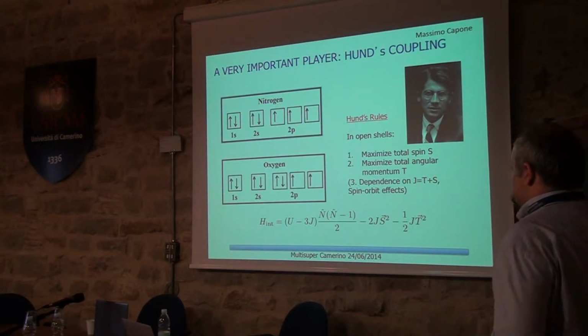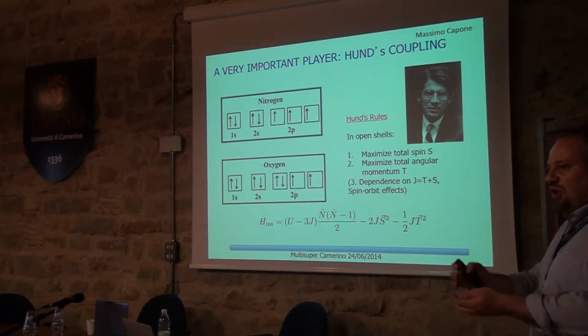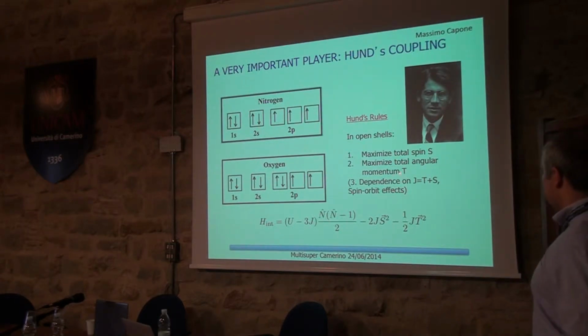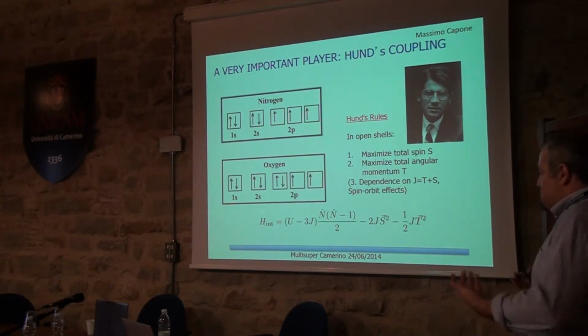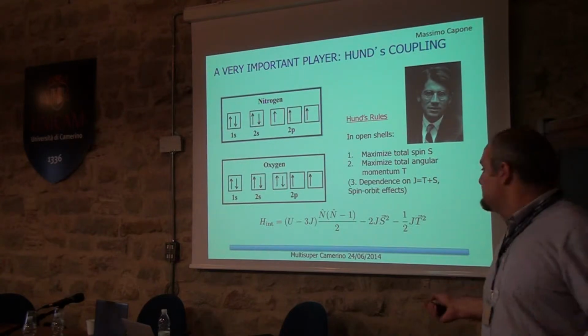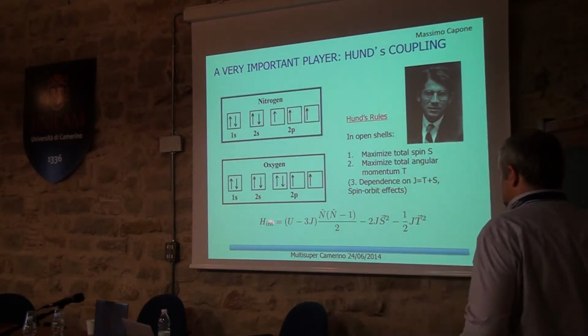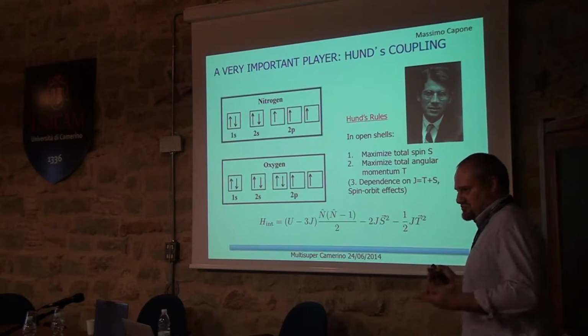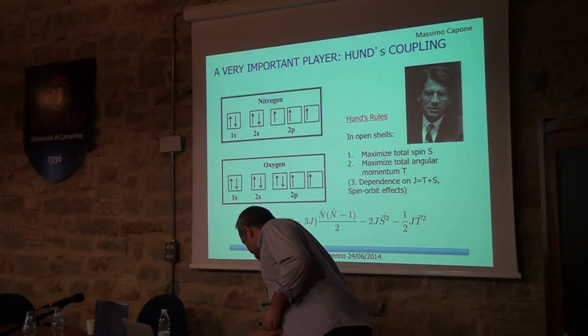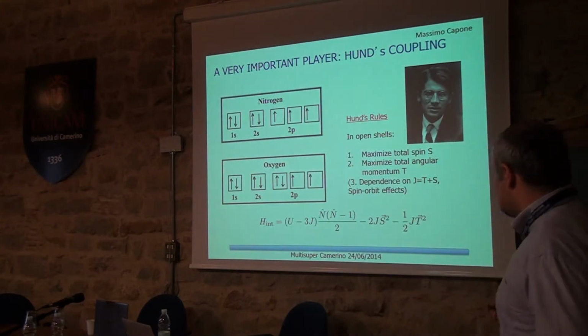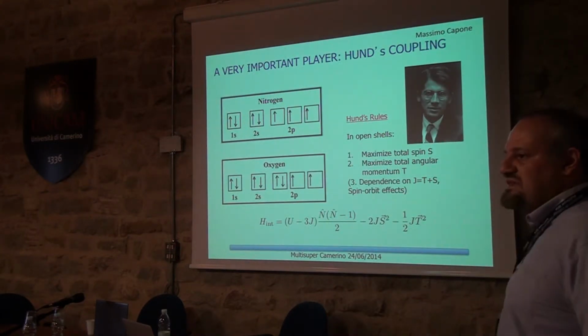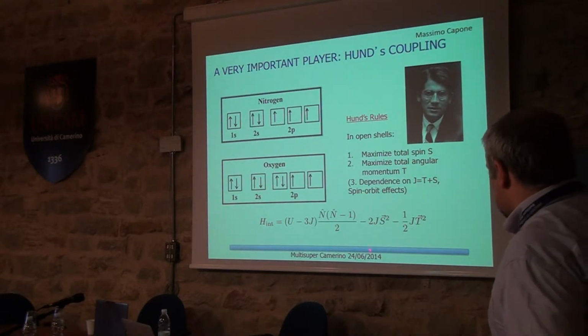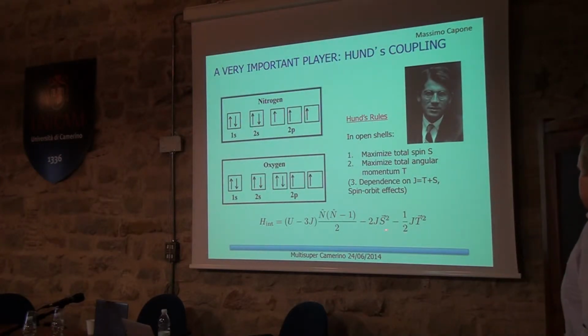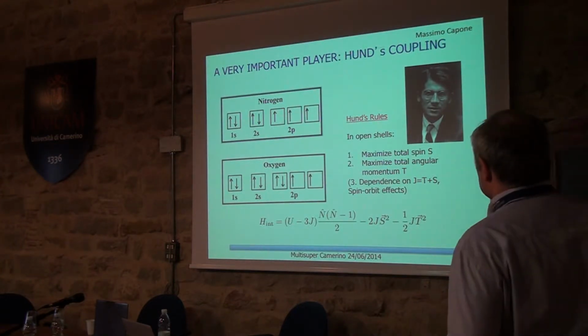It wants to, first of all, maximize the total spin of electrons sitting on one atom, and then, as a second prescription, maximize the total angular momentum on the same atom. The third one is not related to the same exchange, it's just due to the spin-orbit coupling. So this is what you do to build your atomic configuration. That's essentially how it looks when you write it down in the Hamiltonian. This is written in a particularly explicit way that really tells you that you want to favor high spin and high angular momentum.